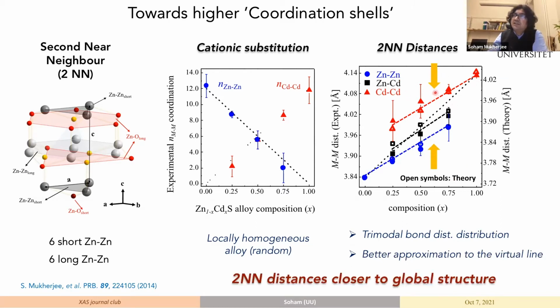As you can see, in the nearest neighbors, these lines were somewhere around there. But now the slope has come much closer to the virtual line. So the take home message from this slide is that the second near neighbor distances from zinc or cadmium both approach much closer to the virtual line, which is basically what is deduced from diffraction.